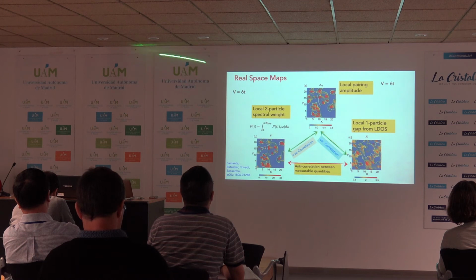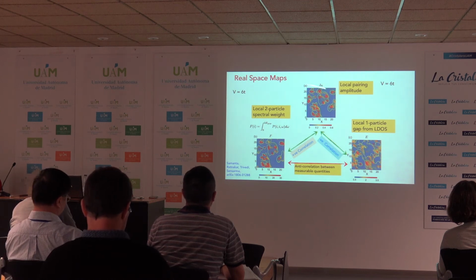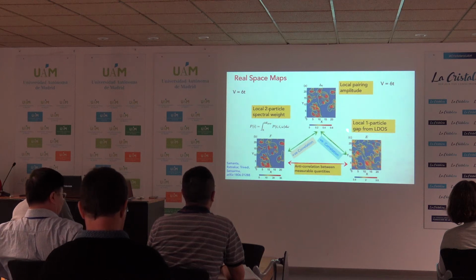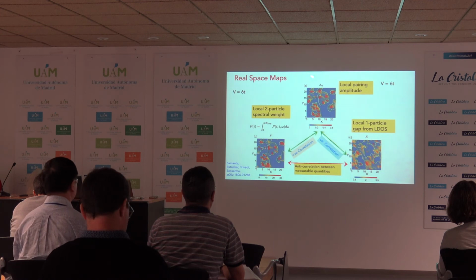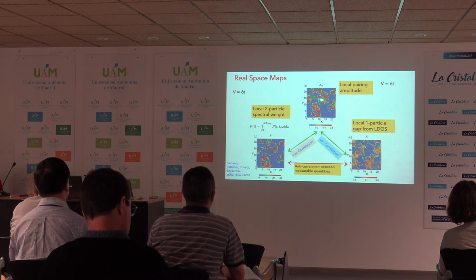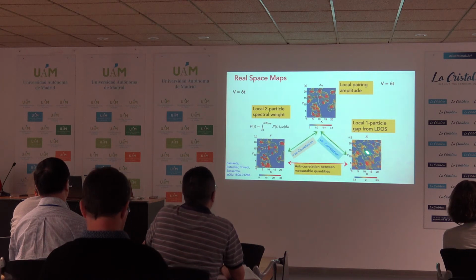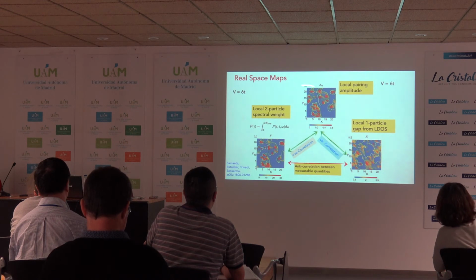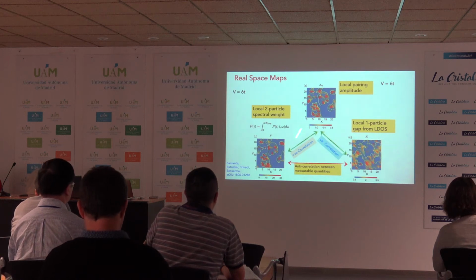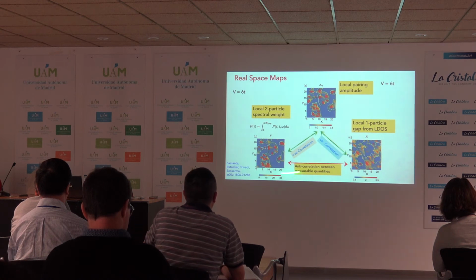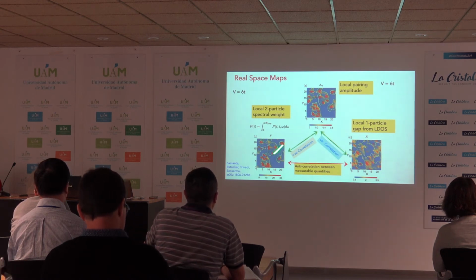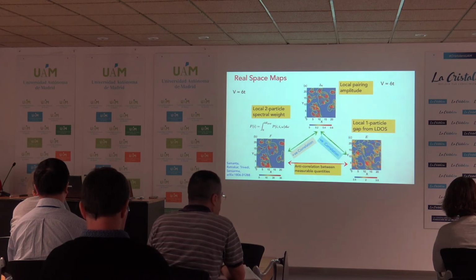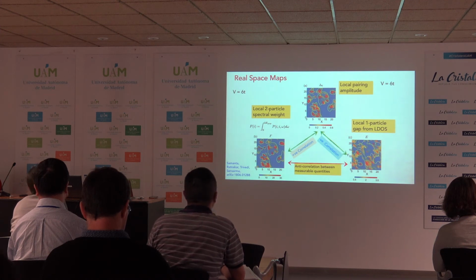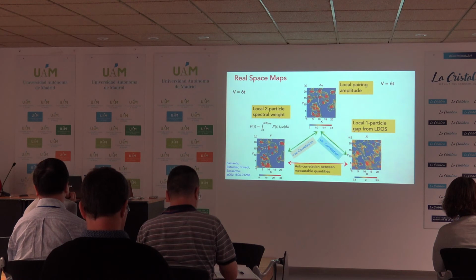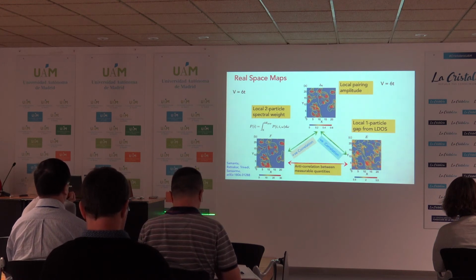So here is a particular value of the disorder, enough to give me these local pairing amplitude patches. This is the one particle spectrum we talked about that was anti-correlated. I have made the same contours and taken from the local pairing amplitude here. So you see that within the contours, while you had a large pairing amplitude, you have a low density of states that we talked about, that anti-correlation. But if you look at the two particle spectrum, that is large precisely on these patches where the local pairing amplitude was large. So that would be an experiment that would be extremely useful, to combine the single particle and the two particle and close this loop.